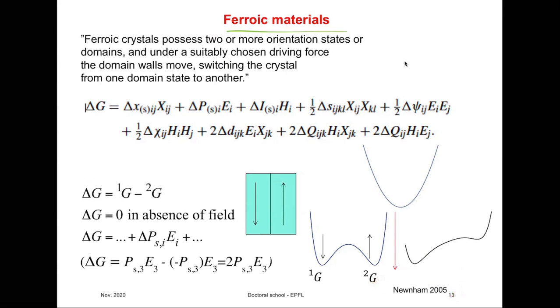There is a whole chapter on ferroic materials, and basically the treatment is the following. You have a cubic material. Okay, there is no polarization. And as you go through the phase transition through TC, you develop these two. So polarization is 0 here. Then we go into the ferroelectric phase. We have two states of polarization, which are equivalent but in different directions. Those two states have to differ somehow.